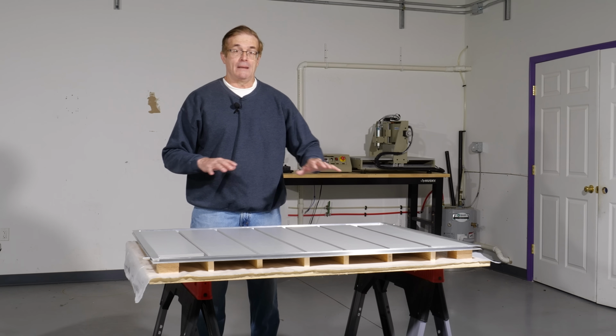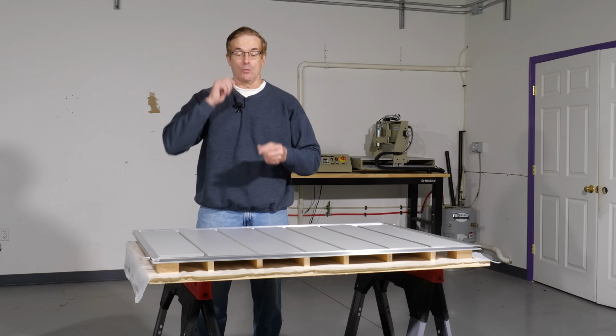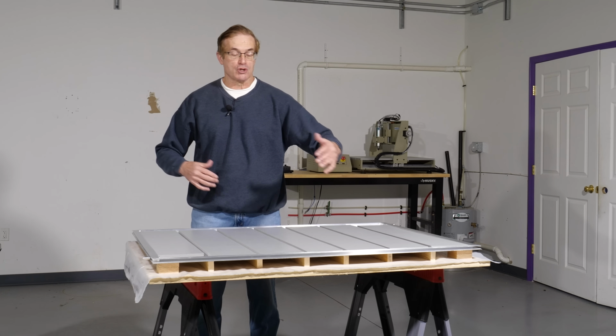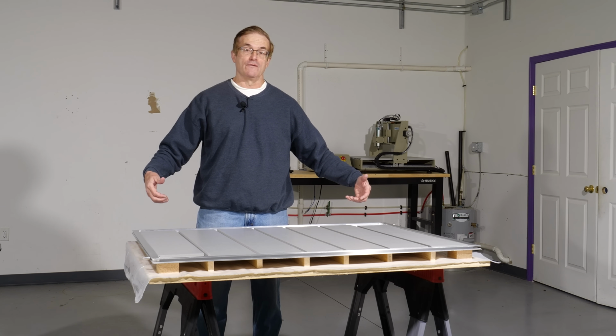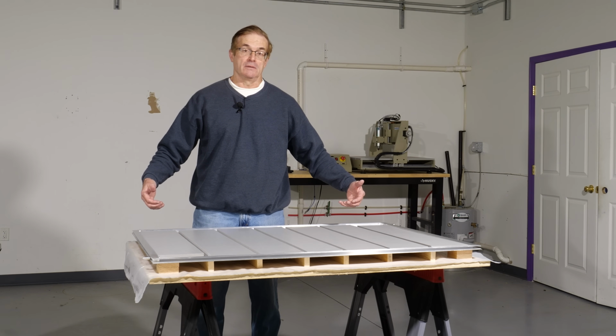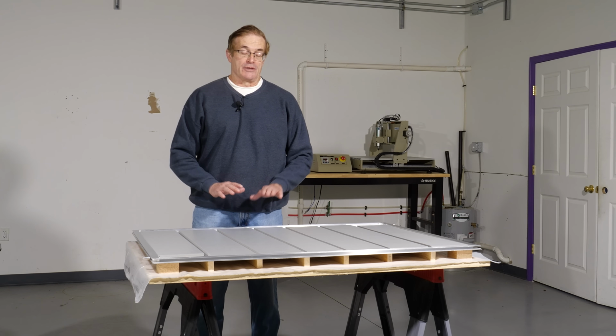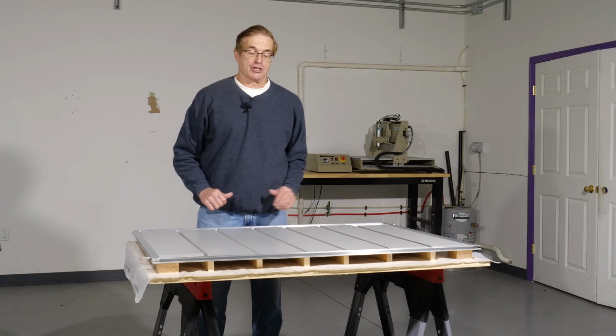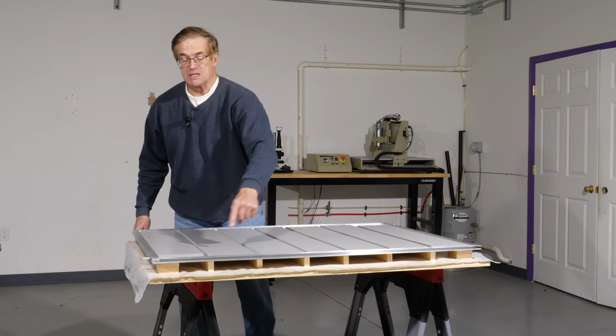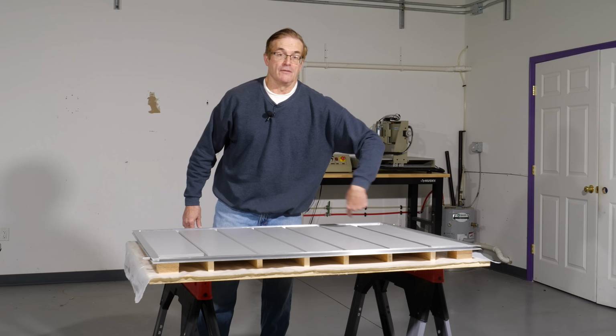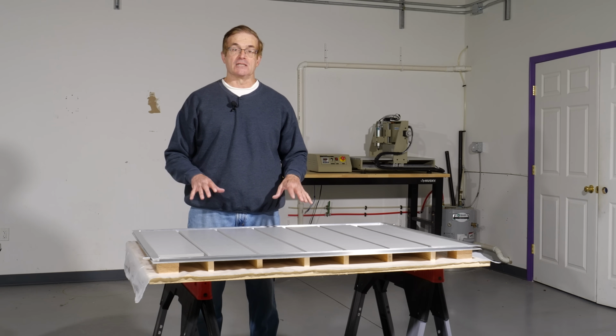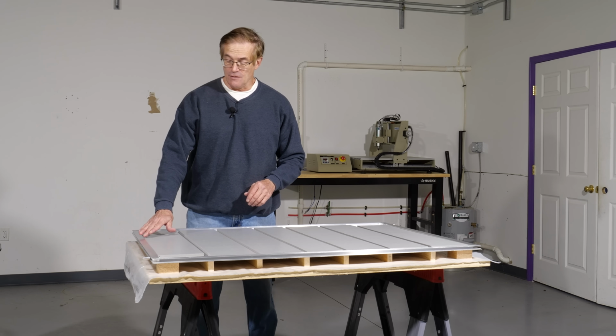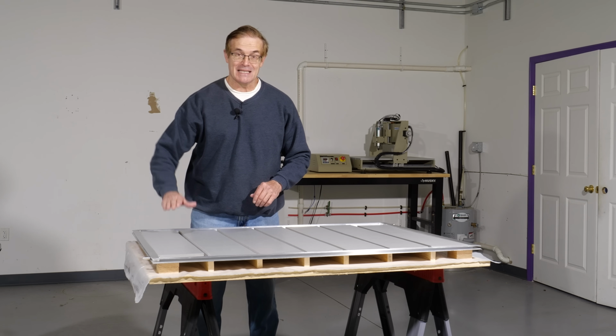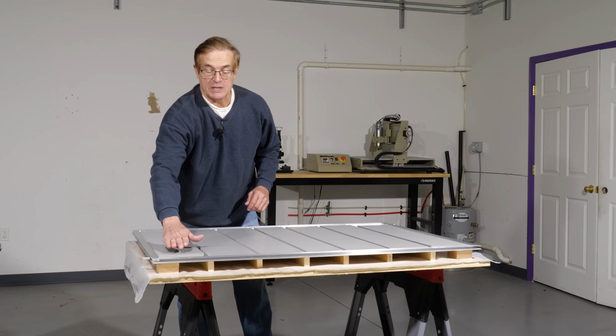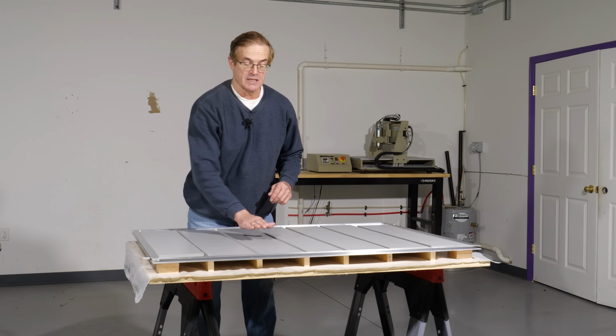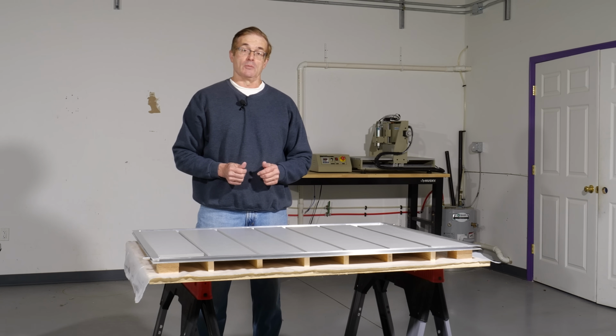Now, one of the problems with this kind of a system is that with a 1.5 centimeter thick, 1 square meter area, this thing would contain, when full, 15 liters of water. It would weigh a lot. So on the surface that doesn't matter, we're not doing the heat exchange, I bonded some closed cell foam to fill up the bulk of the volume inside of here to keep the panel light when it's filled with water. But because these foam inserts are not as thick as the spacing here, we still get a water layer between the front surface and the aluminum, so we get good thermal exchange.